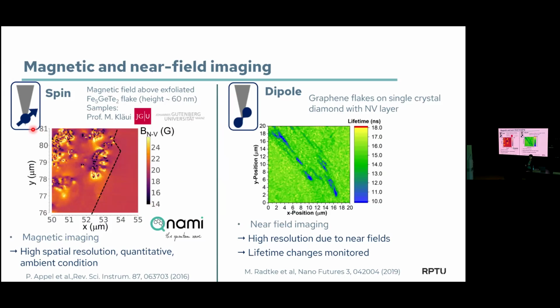You might have realized that I draw the spin here at the tip with an angle towards the tip. And this is because really the NV center is oriented under an angle in the diamond. In our case, typically it's not exactly sticking out of the diamond or in plane. So this is just one illustrative example, right? This is really performed by measuring the Zeeman shift of this resonance. And no, we are not doing this on purpose. It's just that the typical orientation of the synthetic diamonds is 100 diamond. And then you have the NV centers, because they are oriented along a 111 direction, they are oriented under an angle of 52 point something degrees. So it's not on purpose.